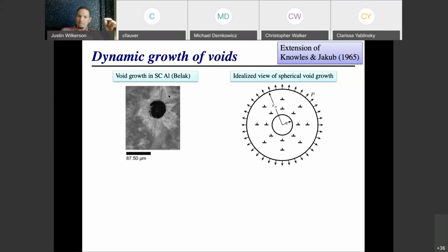In addition to that, something that's fairly unique to voids that we have to consider is there's an inertial constraint. So as I try to grow this void at a very fast rate, there's all this mass that's around the material, and I'm pushing that mass away radially. And there's an inertial resistance to that. If I try to accelerate that mass away at a very rapid acceleration rate, then there's an inertial resistance to that. That's going to work against that, and that's going to slow the dynamics or the kinetics of the growth of that void.